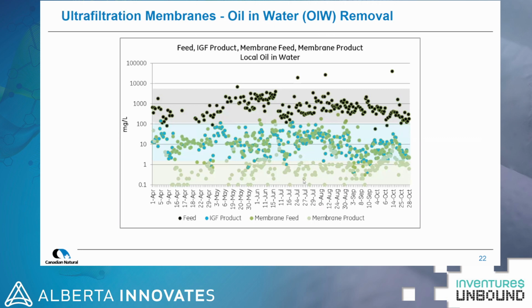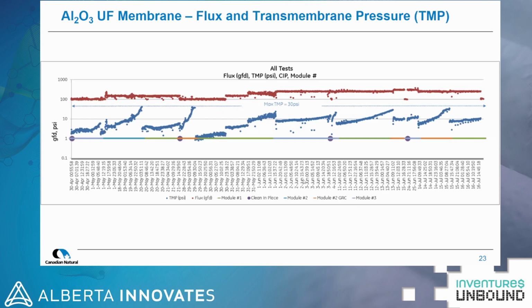Here's some data from operation of the aluminum oxide UF membrane. So this shows flux and transmembrane pressure. So flux being the flow rate divided by the filtration area, and the transmembrane pressure is the pressure across the membrane. The upper line, the red line, is our flux, and the blue lines are the TMP. We had an upper limit of 30 PSI, a max TMP of 30 PSI.